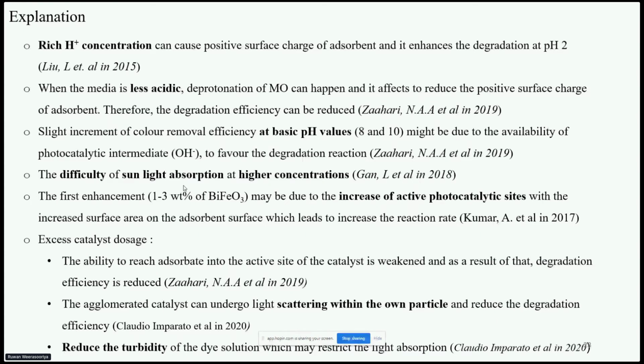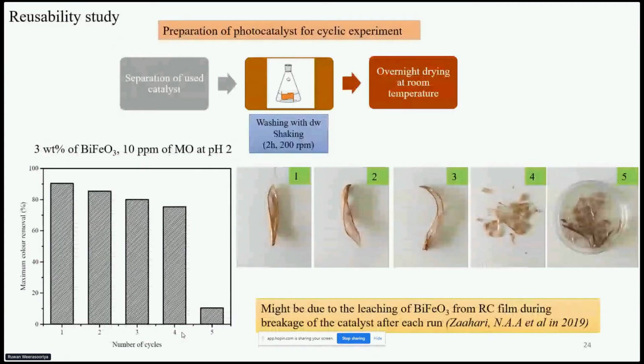When the catalyst dosage is increased, at excess catalyst dosage, as a result of agglomeration, the ability of the adsorbate to reach the active site of the catalyst is weakened and therefore degradation is reduced. Also, agglomerated catalysts undergo self-light scattering within the particle and therefore degradation is reduced. Further, agglomerated catalysts reduce the turbidity of the dye solution, and that also restricts the light absorption and degradation is decreased. Now we have identified the best process conditions to obtain a maximum degradation.